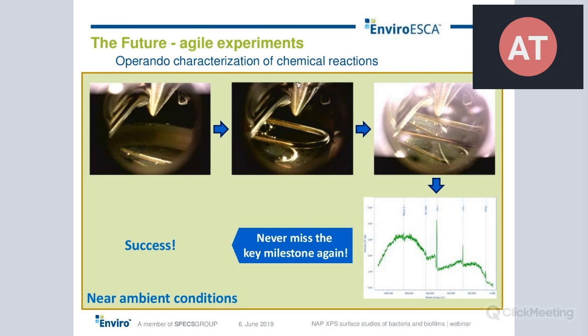So what does that mean for our etching experiment? This means you insert the paper clip together with the acetic acid into the machine, and then you come close to your sample with your nozzle. This is the entrance of your analyzer. And then you look for a position where the layer of the liquid of the acetic acid is so thin that you can measure through the acetic acid and still see the paper clip.